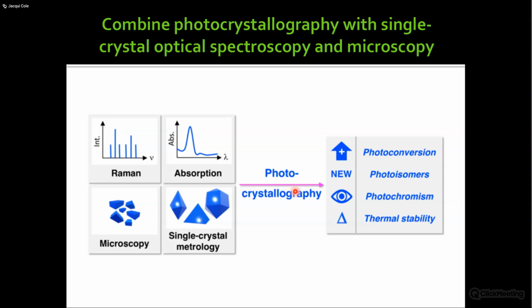Together with the photocrystallography, we do a lot of optical absorption spectroscopy, but importantly, not the typical optical absorption spectroscopy that happens in most labs. We're doing single crystal, low temperature optical absorption spectroscopy, which is essentially not a commercial apparatus to my knowledge, and we've had to build our own to get this to work. And likewise with Raman spectroscopy, I'm not showing any today actually, but in that case we use the light of the Raman spectroscopy to excite it, and then use temperature to play games to switch on and off the light induction so we can see the vibrational spectroscopy.